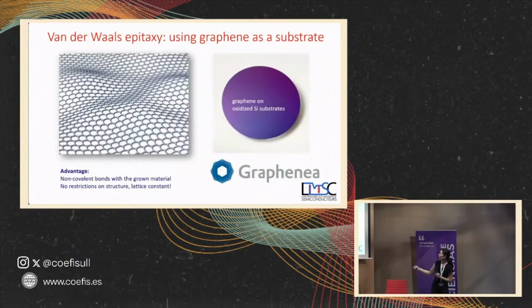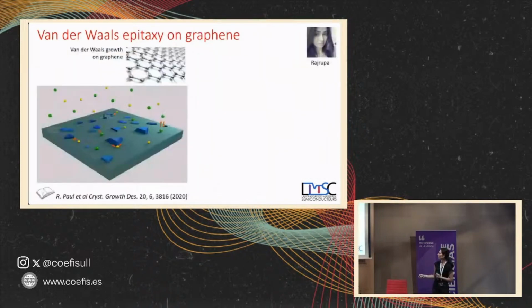To grow on graphene, we use a commercial substrate from a Spanish company, Graphenea. They're in the Basque Country, and they sell you very big substrates with graphene on top. And you can just use this. You can buy it, and it's always the same, so it lets us do the experiment. So when we start this, there is a problem if we want to grow on graphene.